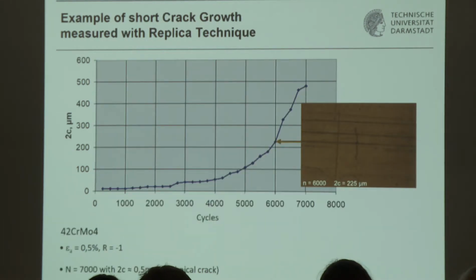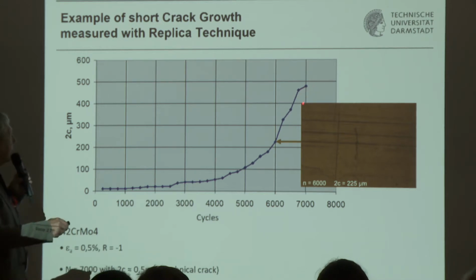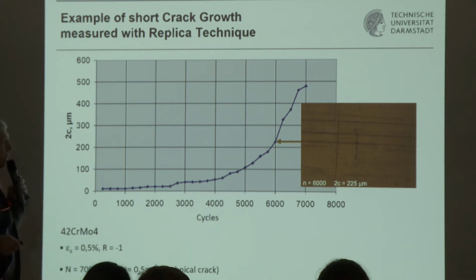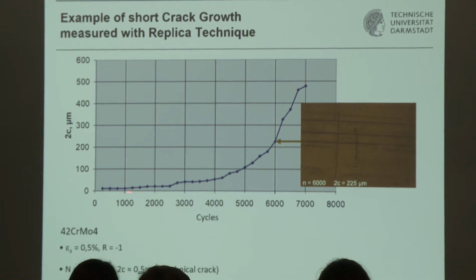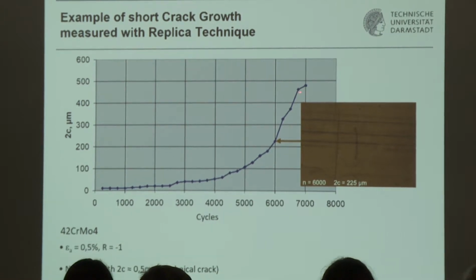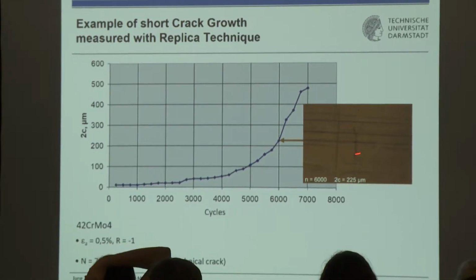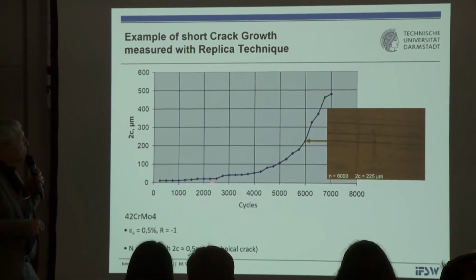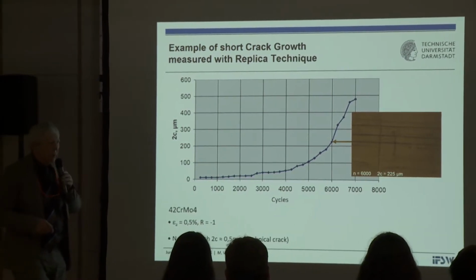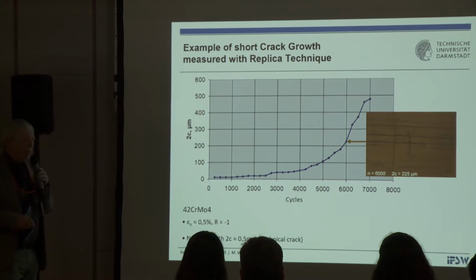Coming back to fracture mechanics and fatigue crack initiation, it is a good idea to study what has happened before this crack has initiated. Other than we just heard regarding brittle fracture, we know that before arriving at a technical crack of a millimeter size or so, there has been crack growth in the stage before that. If you are lucky enough to have photographs of the site of crack initiation in an earlier stage of life, you will be able to identify that this crack has been there for nearly the complete lifespan.